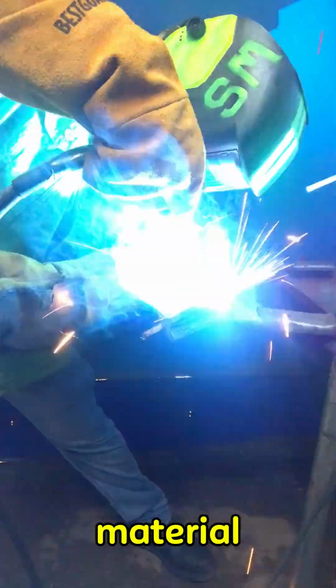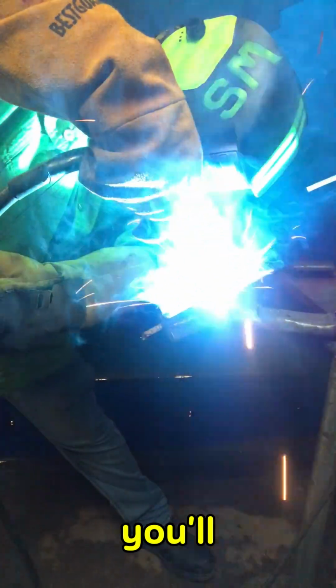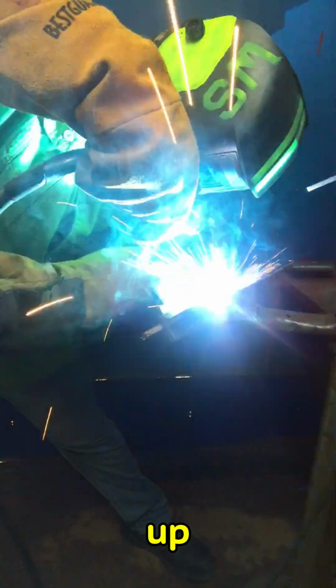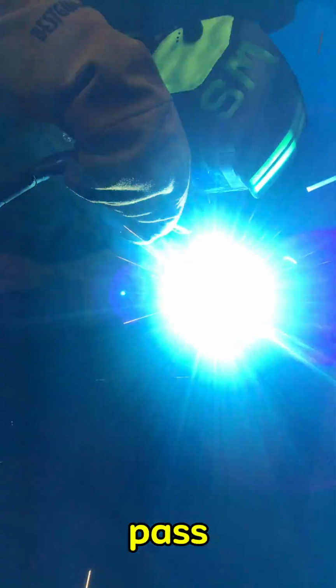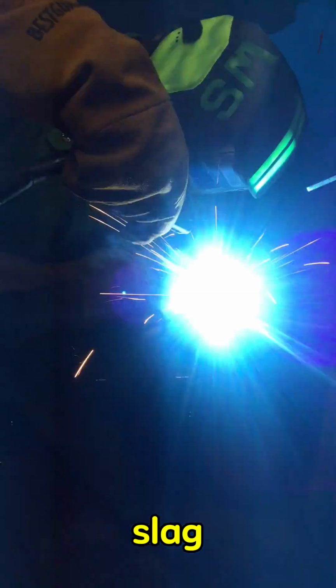Mistake number 5. Trapping slag during multi-pass welds. On thicker material, a single pass isn't enough. You'll need 2 or 3 passes to build up proper leg size. A massive rookie mistake is running pass number 2 directly over the slag or glass left by pass number 1.